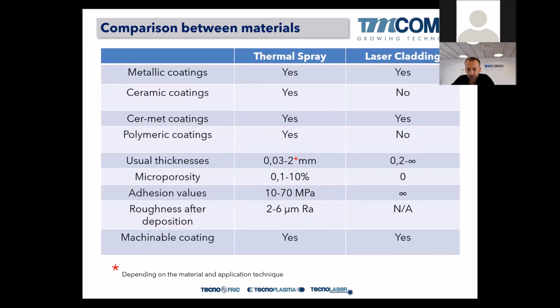Polymeric coatings in thermal spray, yes. Laser cladding, no. The usual thicknesses in thermal spray are 30 microns to 2 millimeters, more or less. 2 millimeters is not for all materials. In ceramic and cermet coatings, we are restricted to 0.5 millimeters, while in metallics, by flame spray or by arc spray, we can achieve 2, 3, 4 millimeter thickness layers, depending on the metallic alloy.